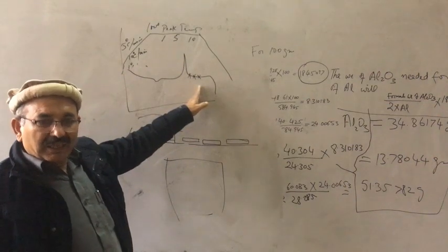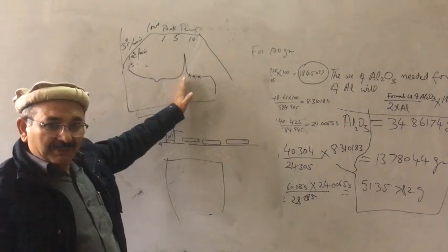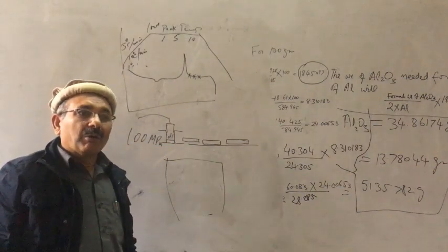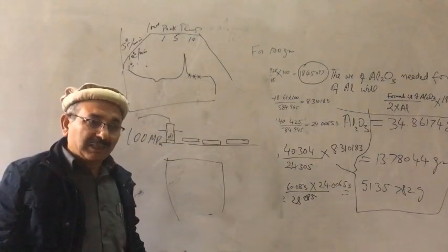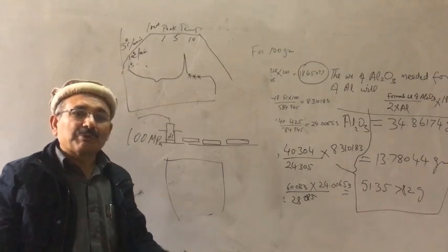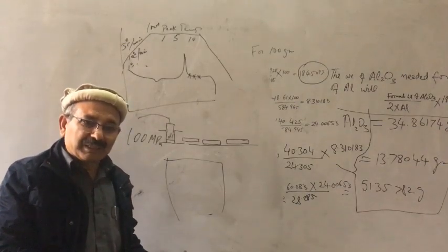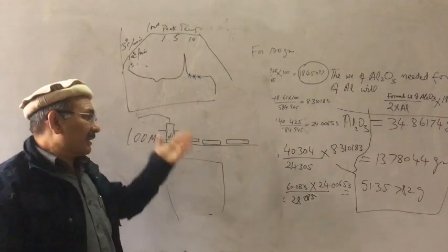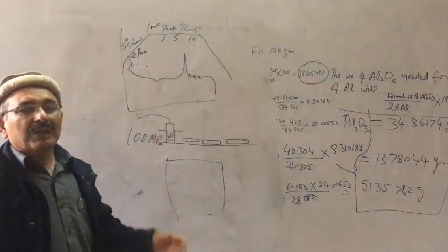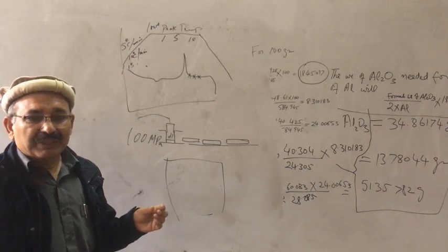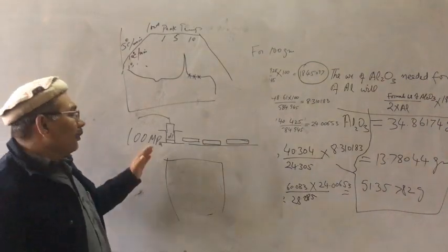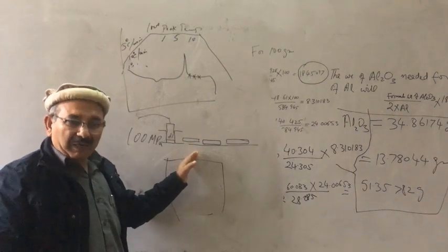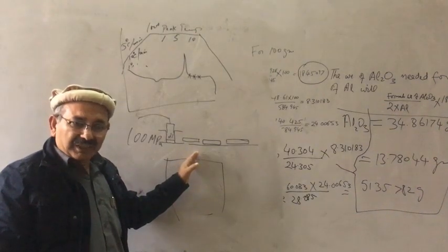It is above the crystallization temperature, or you can say the calcination temperature, well above the calcination temperature but well below the melting temperature, because you don't want to melt the material, and secondly you want to densify the material. So no phase formation is expected during sintering.